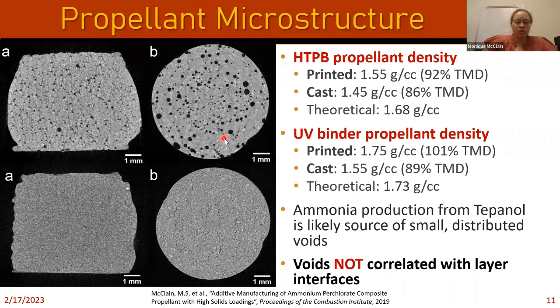And then also, if we compare these cast samples to these printed samples, in both cases, the density improved in the printed samples. So the printing helped us improve some of our porosity issues in the HTPB, but in general it was not the main cause of these defects that we saw. Once we tested this microstructure, we did burn these propellants and we found that 3D printing did not negatively affect how they burned overall. That was very promising for us.